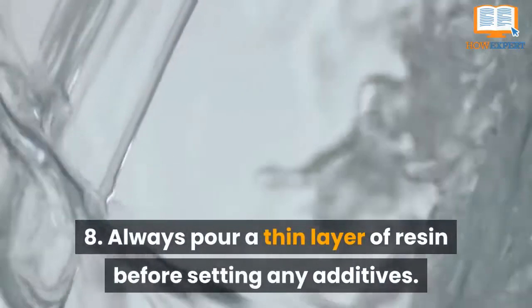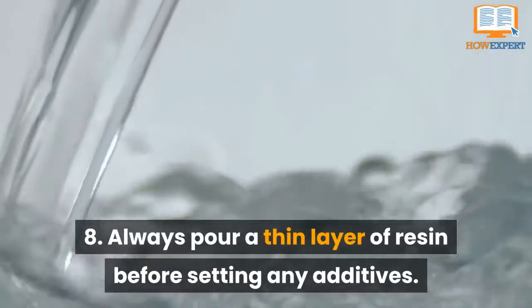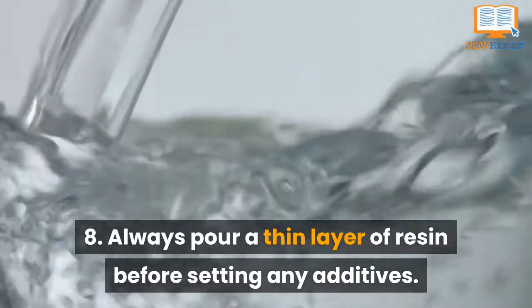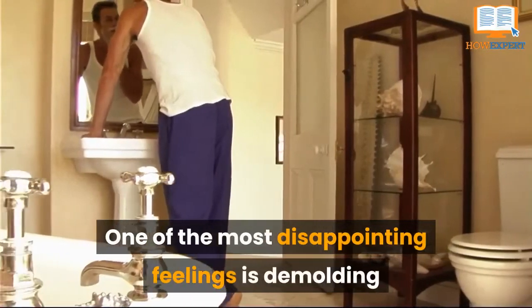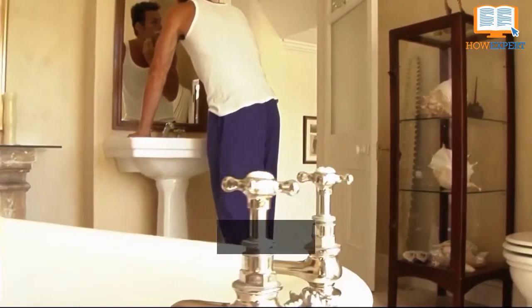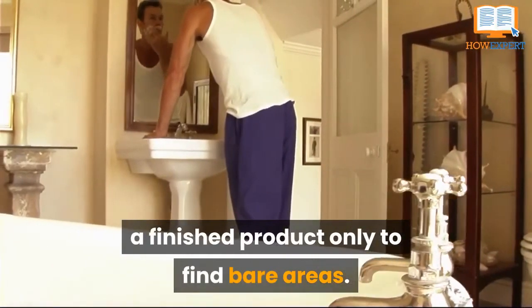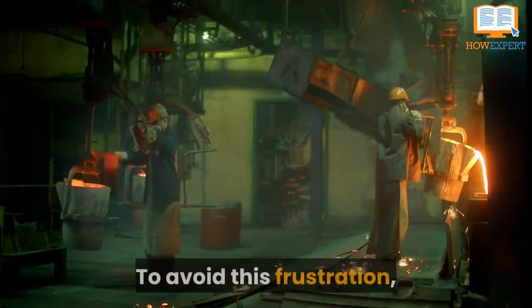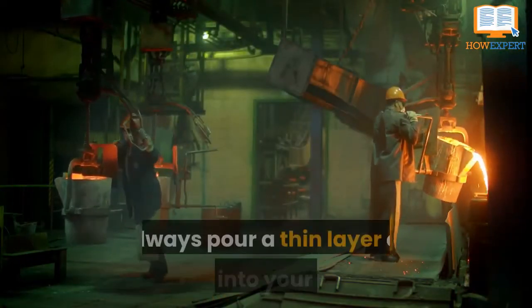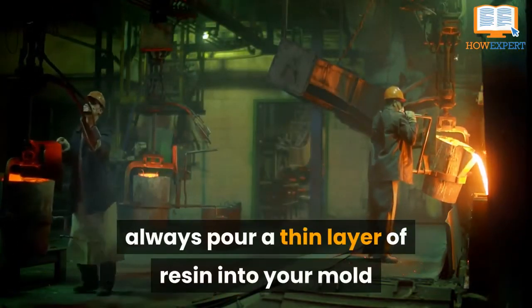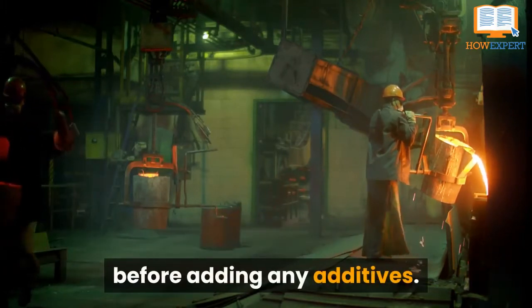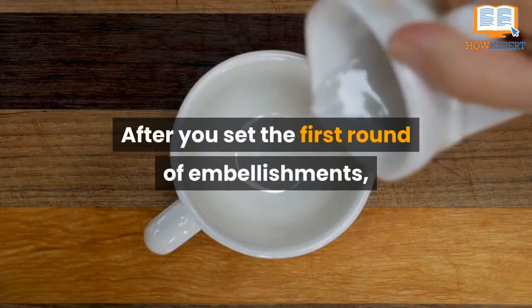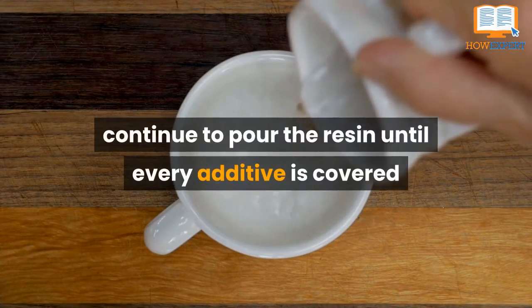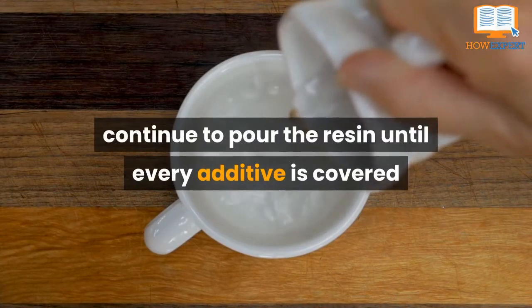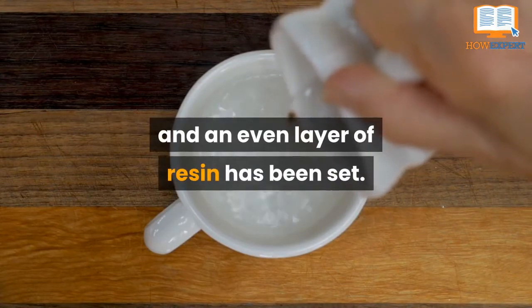Number 8. Always pour a thin layer of resin before setting any additives. One of the most disappointing feelings is demolding a finished product only to find bare areas. To avoid this frustration, always pour a thin layer of resin into your mold before adding any additives. After you set the first round of embellishments, continue to pour the resin until every additive is covered and an even layer of resin has been set.